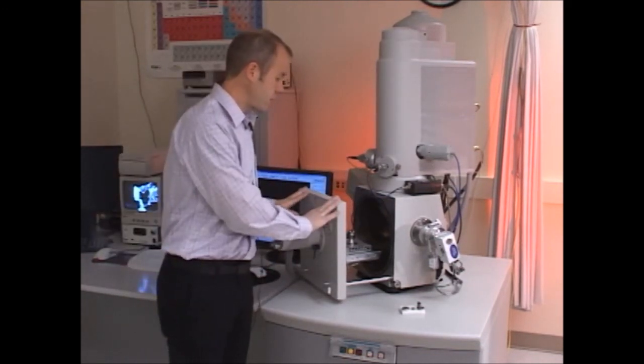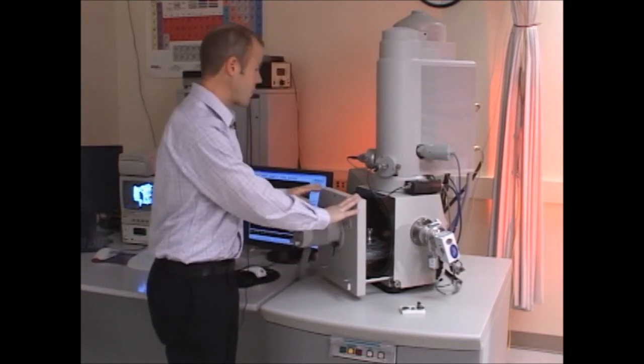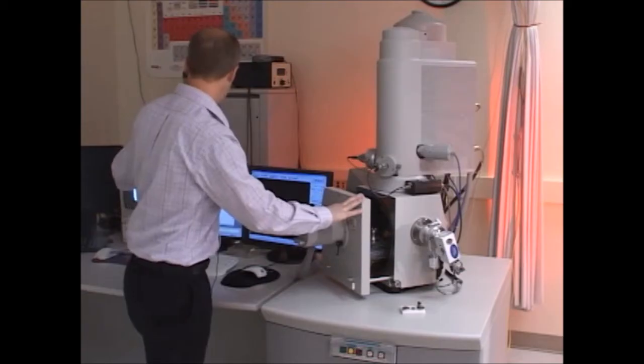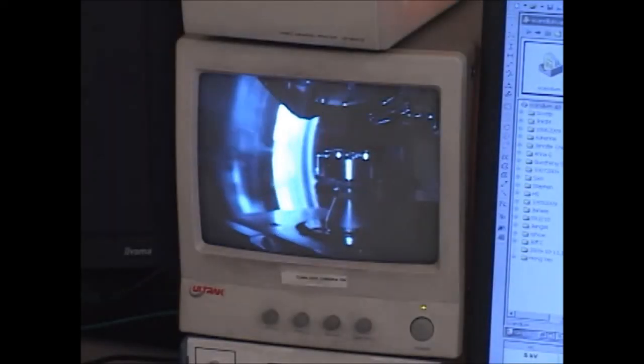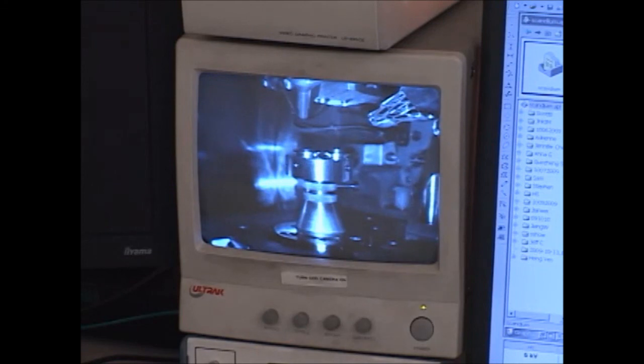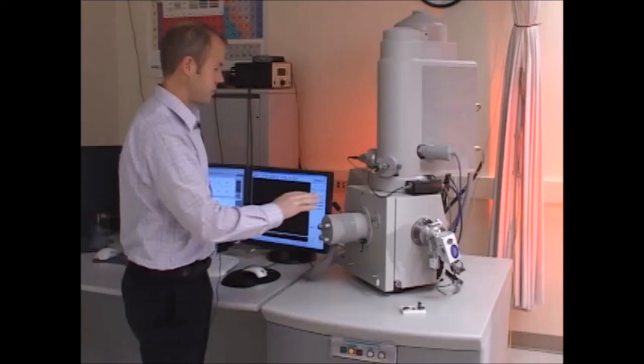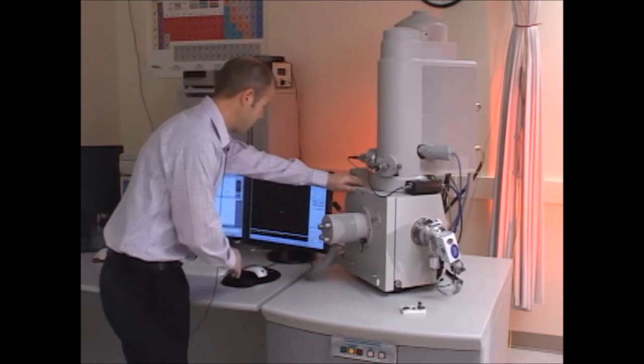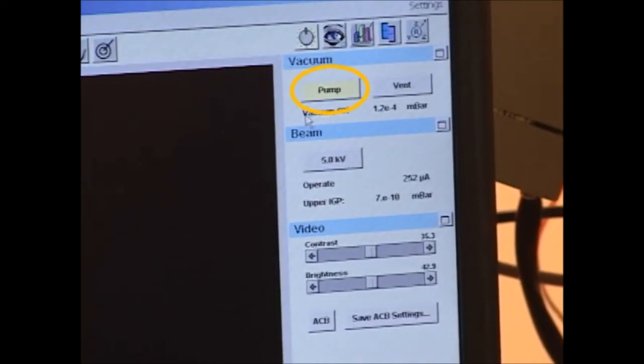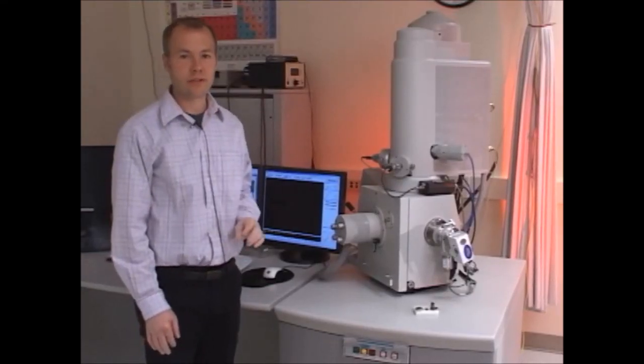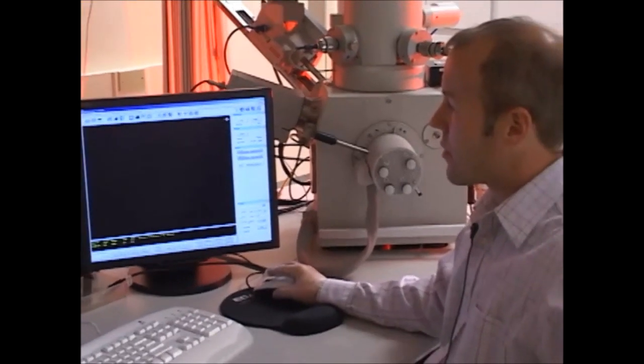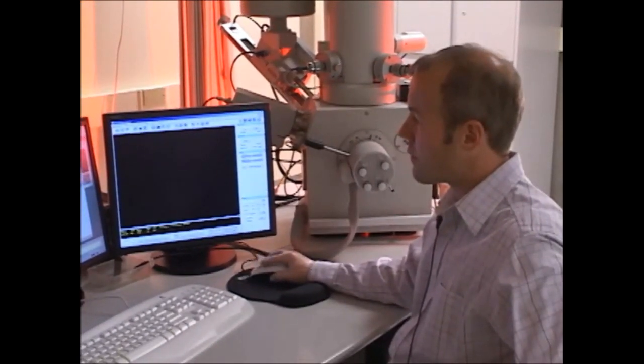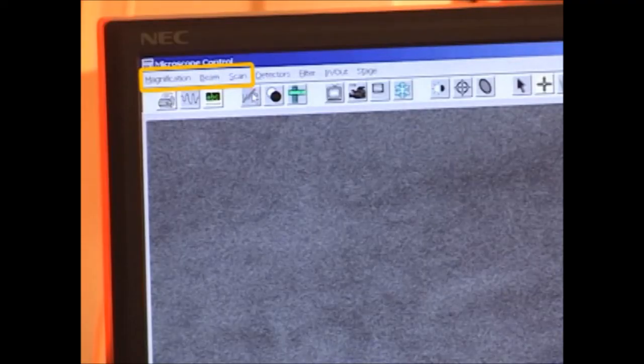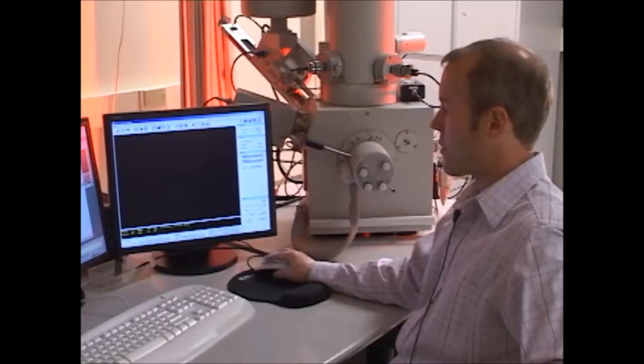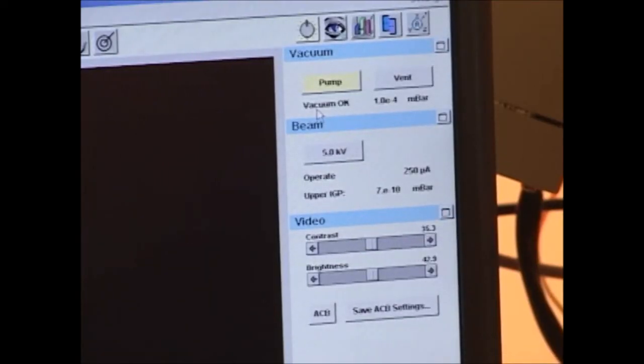And then I'll push the chamber door closed while I'm watching on the CCD camera to make sure that the sample slides in underneath the detector and it's not approaching the height of the detector. Once the chamber door is closed, I'll hold it with one hand and re-engage the pump. It takes about 2 minutes before it reaches vacuum. At that time we can open the column valve and actually view the sample. Most of the software that we're going to use today is located in the first 3 tabs, Magnification, Beam, and Scan. And also the 4 submenus on the right are the blue bars: Vacuum, Beam, Video, and Stage.